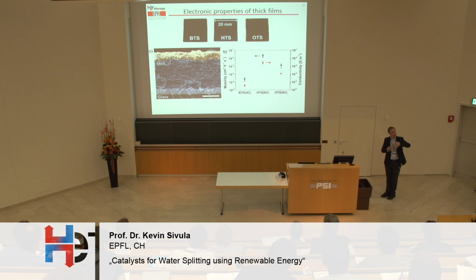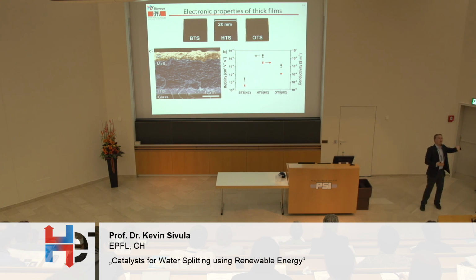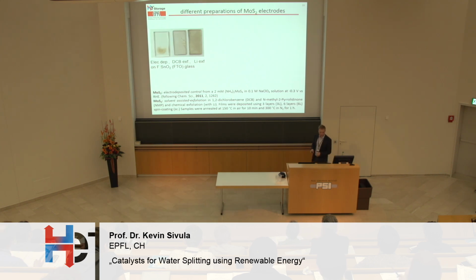Whereas the OTS now is too long and acts as an electrical insulator to stop charges from passing from one flake to the next. The happy medium here is the 6-carbon HTS type of material, and we proceeded on with this to try to make thinner films on conductive substrates to measure their catalytic performance. So here are some films that we've made as electrodes to reduce water into hydrogen, and we've used a standard procedure that's published to make electrodeposited molybdenum sulfide, and also used spin coating with annealing at a low temperature to produce our films here, which are relatively homogeneous and easy to produce.